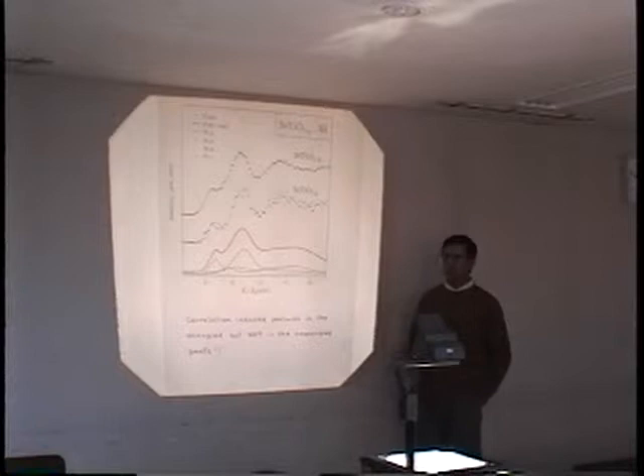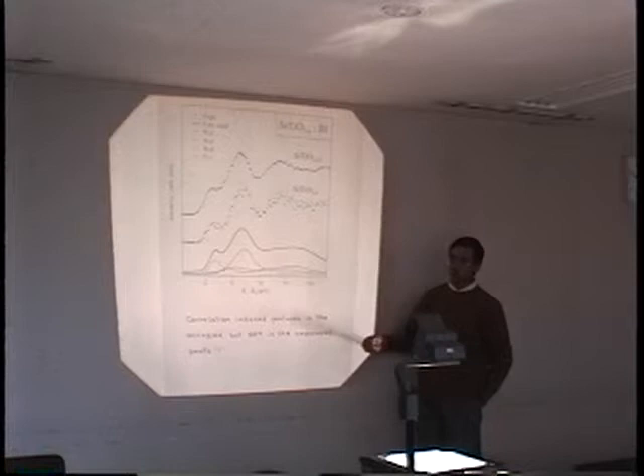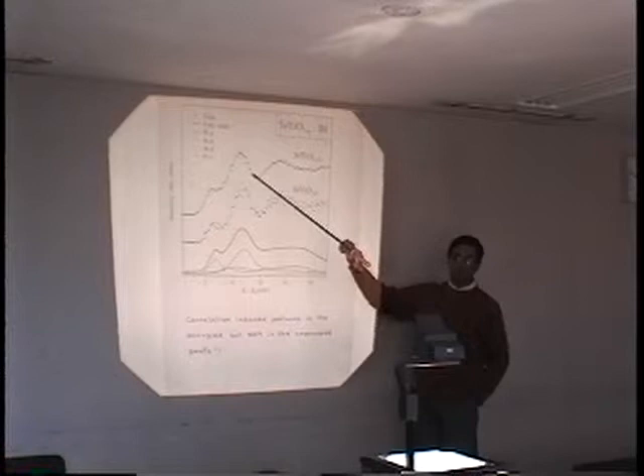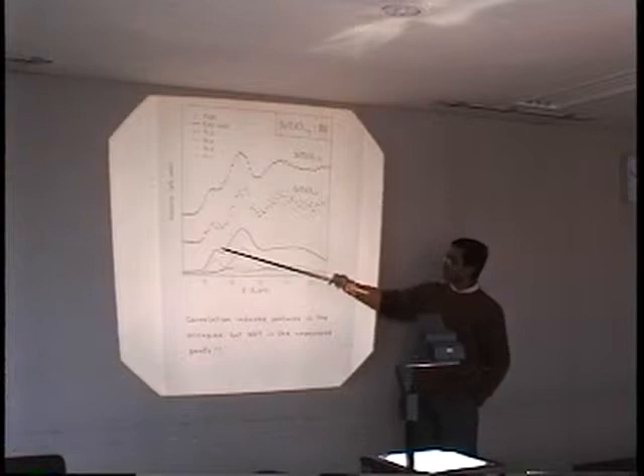If there was such a strong correlation-induced satellite in the occupied part, you would expect a stronger correlation-induced satellite in the unoccupied part. But the unoccupied part is exactly describable by band structure calculation.